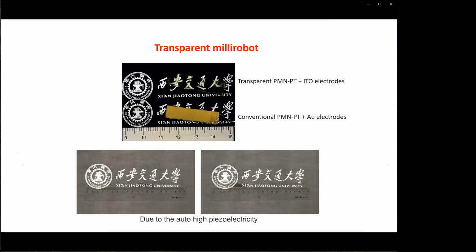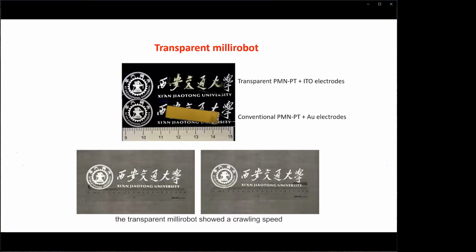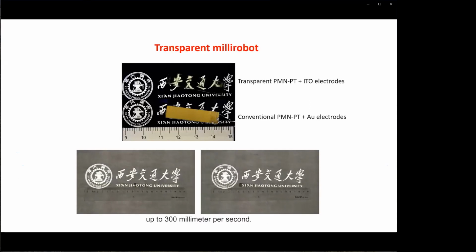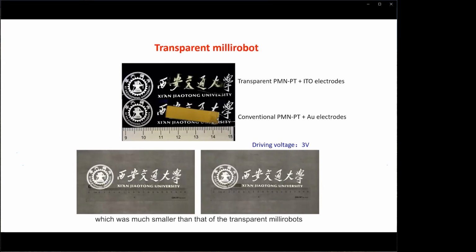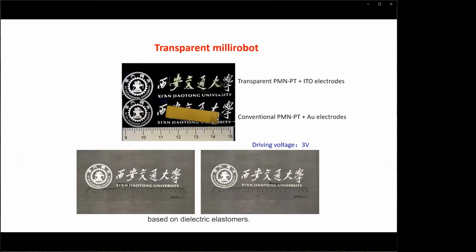Due to the ultra-high piezoelectricity of the transparent PMN-PT crystal, the transparent milli robot showed a traveling speed up to 300 mm per second. In addition, the minimal driving voltage of this robot is just 3 volts, which was much smaller than that of the transparent milli robots based on dielectric elastomers.